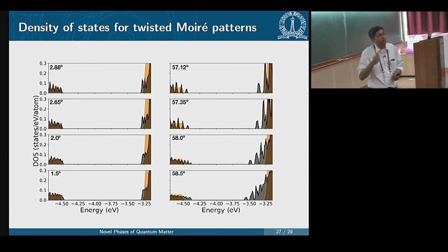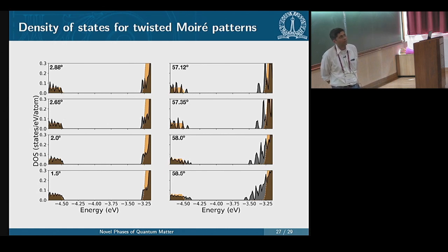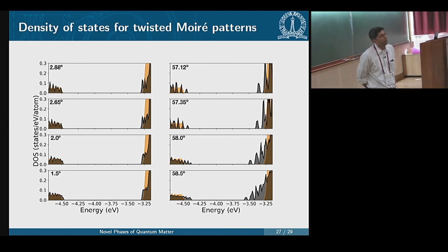We've tried putting spin orbit coupling in, to see how this valence band hybridization changes. It turns out near 0 degrees, near the gamma point, spin orbit coupling is anyway 0 in these systems, so it doesn't really make a difference. Both of the bands, this flat band, are occupied in our calculation. It's an insulator, so both up and down are occupied, and there's nothing happening there.